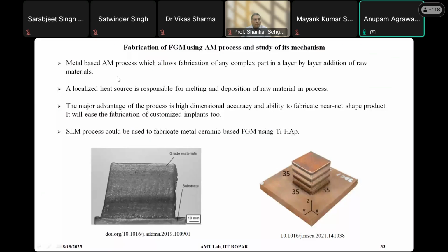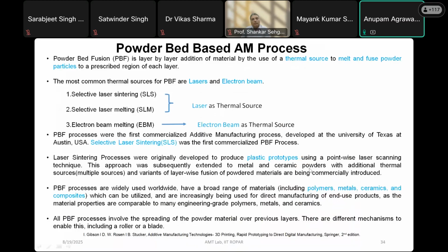What we are trying now is to pre-mix the powder of titanium with hydroxyapatite in different percentages and keep it ready for layer by layer fusion. So far we are successful in making only one single percentage of titanium and hydroxyapatite mix, but our target is to vary the percentage as we grow. Powder fusion based processes are quite good at achieving this, but multi-material is a challenge.